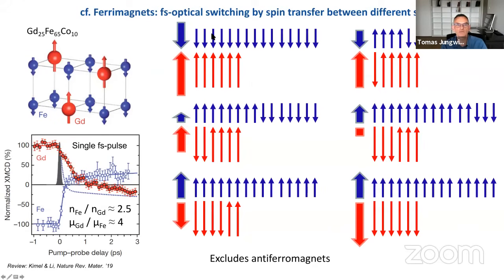So imagine that you start with this perfectly ferrimagnetic antiparallel phase of these large moments being gadolinium and the smaller moments being iron. Now, when you excite the system with a strong femtosecond laser pulse, you start demagnetizing the system, which means in principle that you start flipping the spins. But if you want to conserve the total angular momentum, flipping one gadolinium spin would then correspond to flipping approximately 4 iron spins, and the total angular momentum is conserved. When you go to the next step of the demagnetization, you flip the next gadolinium spin, and you flip the next 4 small spins, iron spins.